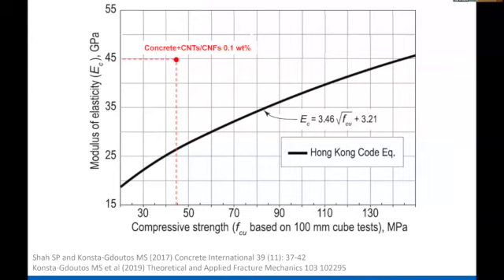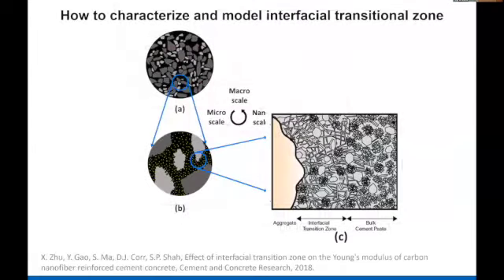Now, why are CNT or carbon nanofiber proportionately more effective in concrete than in cement paste? Well, clearly you can probably see the idea is the interface.